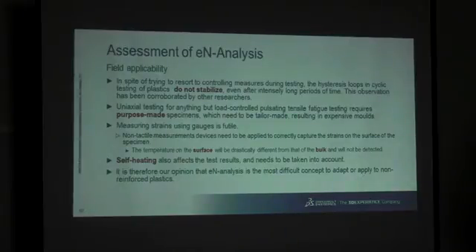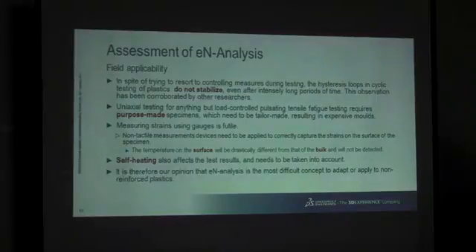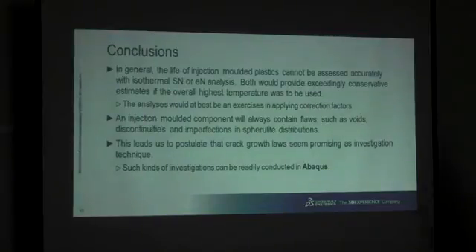EN was much more tricky because all of the research, not just ours but out there, shows that you don't have stabilized hysteresis loops. They don't exist. You have to use purpose-made specimens for specific testing. You have self-heating, and there is no point in trying to measure strains using gauges. Because what you're doing is you are applying these gauges to the surface with something like epoxy resin or similar. Which means that for some plastics, what you are measuring is actually the glue and not the properties of the plastic itself. So if you want to do something, you have to use non-tactile measurement skills. Nothing else works.